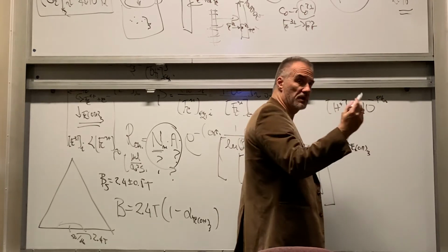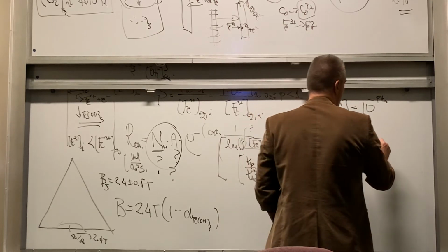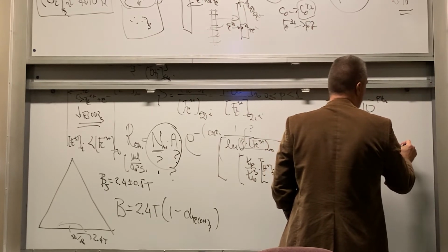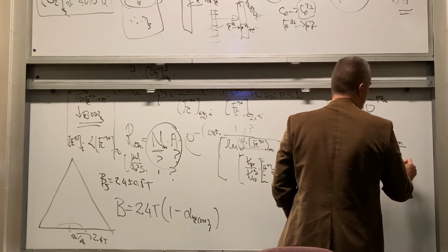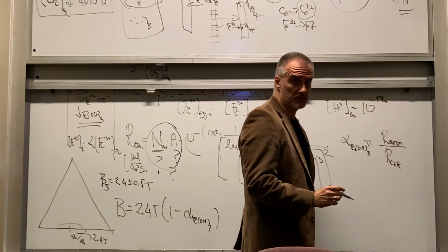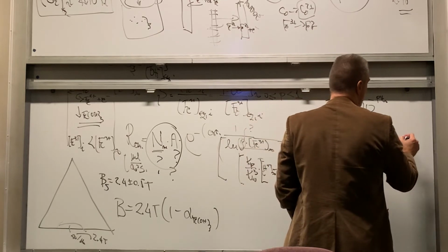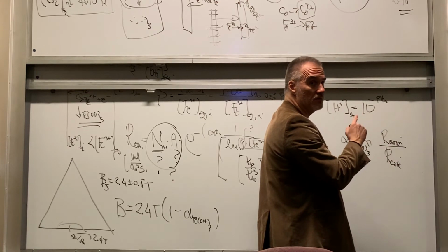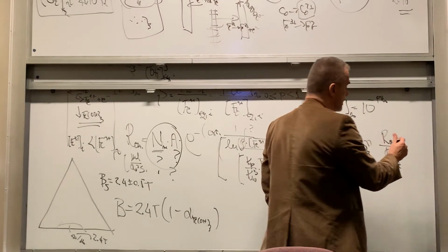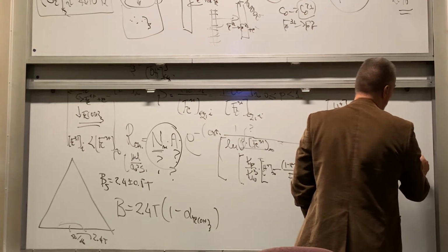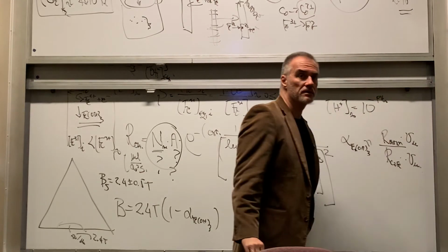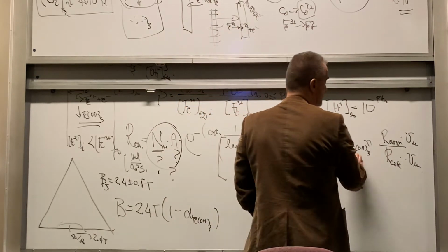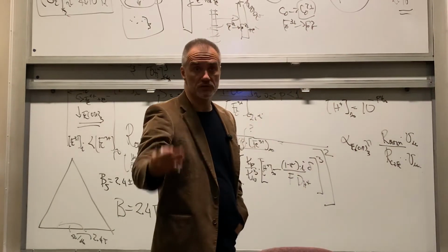I can give you a clear formula, which is longer, but I'm going to just say it is approximately the rate of incorporation of the hydroxide phase, then the rate of deposition of cobalt iron phase, times, because this is the rate and I want to get the volume, this has to be multiplied by the molar volume, and you get basically the ratio in terms of the dimensionless number, such as fractional volume, okay?